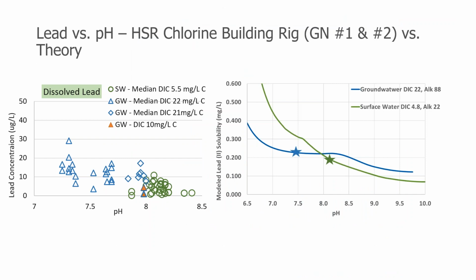So how does this compare to our desktop theory, just in terms of lead solubility? The blue, whether it's triangles or diamonds, these are all groundwater, and the green is the surface water. And we see pretty much the trend that was expected of the groundwater being higher lead release than the surface water at those pHs. But if we look just within the groundwater, which is just the blue, it's pretty flat line lead release across this whole pH range, 7.3, 7.4, all the way up to almost 8. It's pretty flat line, which is what theory would predict for the cerussite groundwater at this DIC level. There's maybe some improvement, but it's pretty flatlined.